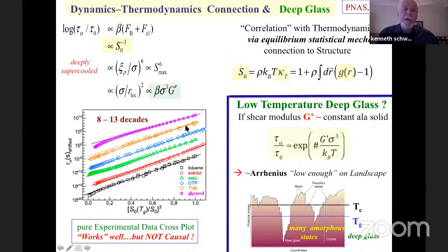This is experimental data, and it's plotted as log relaxation time versus 3 inverse powers of the dimensionless compressibility. And so this prediction would have support if the data lies on a line. And of course, it doesn't perfectly lie on a line, but it lies well on a line in the deeply supercooled regime, which is what this prediction is for, over something of the order of 8 to 13 orders of magnitude. So it works well, which is consistent with the theory, but it's not causal.